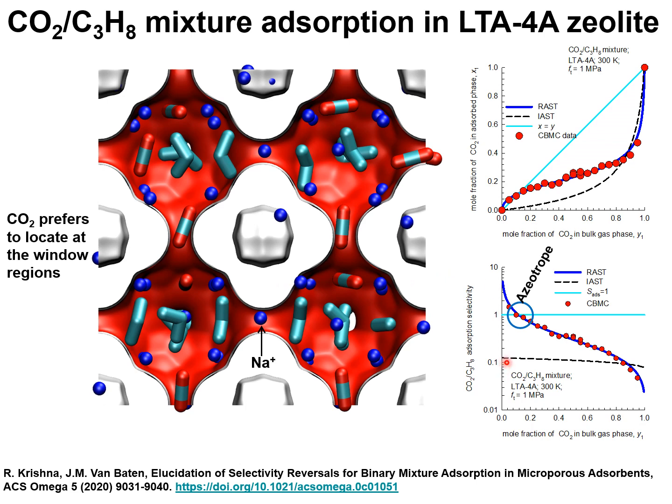Therefore, at low mole fractions of CO2 in the bulk phase, the selectivity is in favor of CO2, because the CO2 does not face stiff competition because it is isolated and locates at the windows.